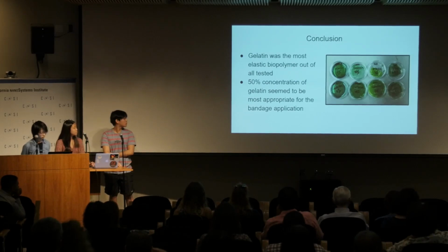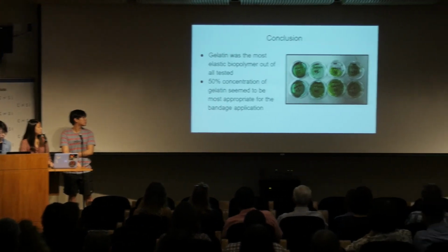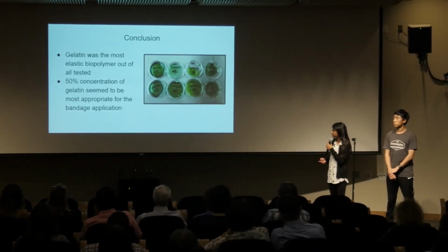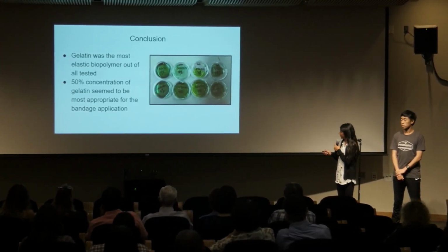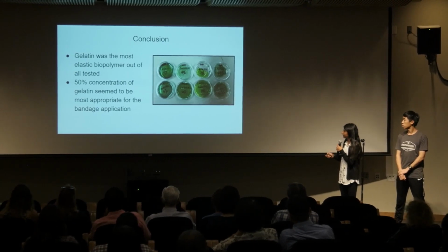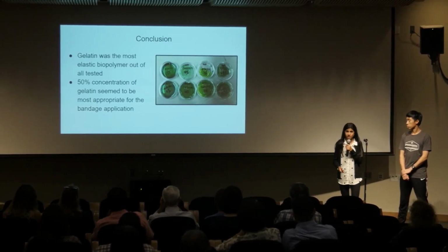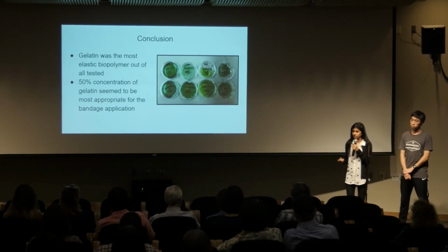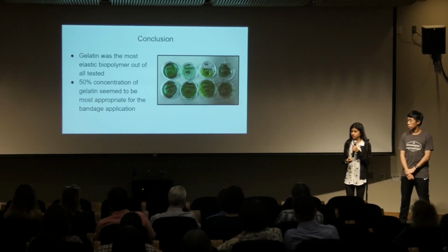So in conclusion, what we found out is that the gelatin was the most elastic biopolymer of all the ones that we tested. And this one right here, the 50%, was the most appropriate for bandage application because it was stretchy enough to fit any wound, like a heel where it has to stretch around. But it also has the appropriate thickness and sturdiness that it can last a long time.